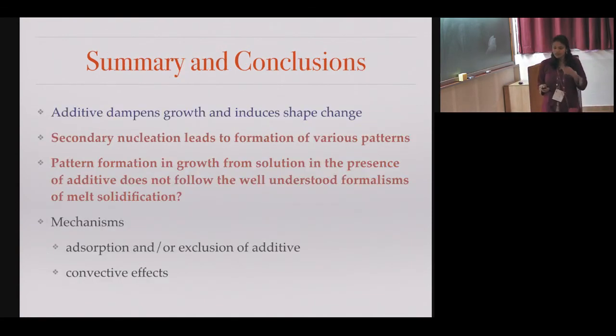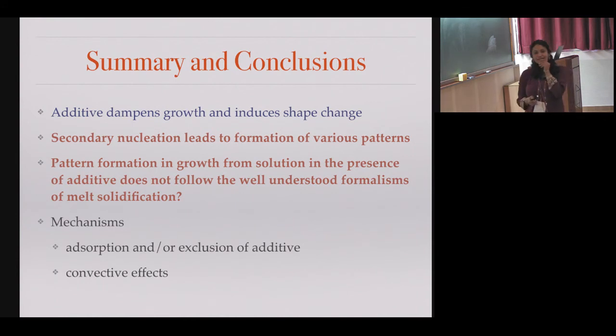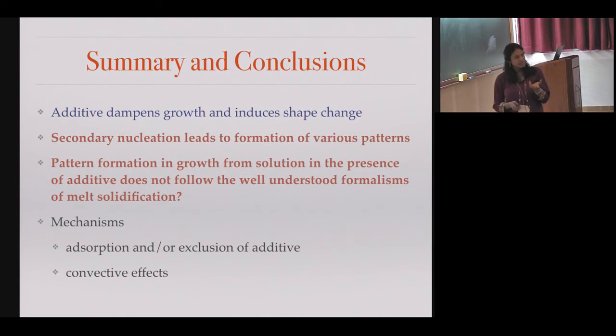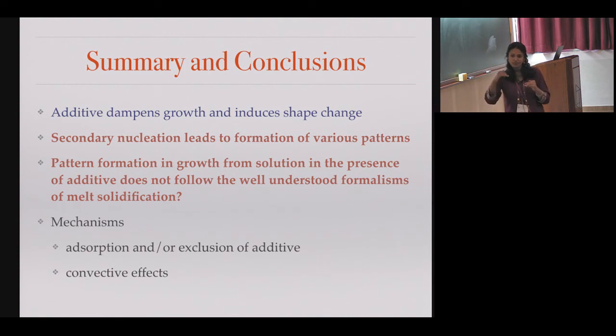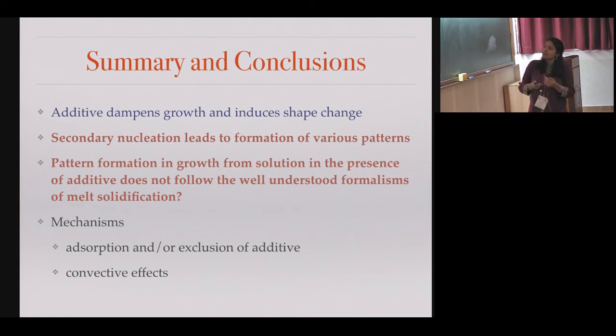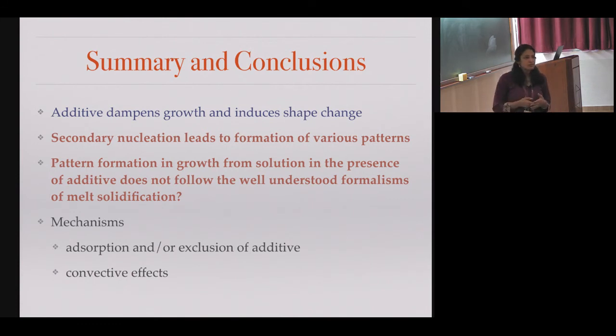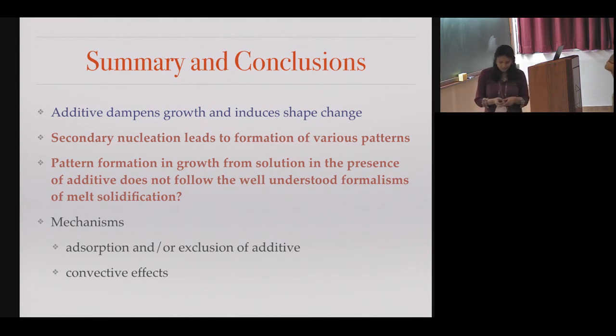To summarize: we don't understand this completely, but the additive dampens the growth rate and promotes secondary nucleation because growth rates are slower. We have confirmed experimentally that secondary nucleation gives rise to the branching — we see bright spots at the nodes under crossed polarizers. The mechanism must be different from melt solidification, and theoretical ideas we are exploring include adsorption of additives on the crystal faces or possibly convective effects.